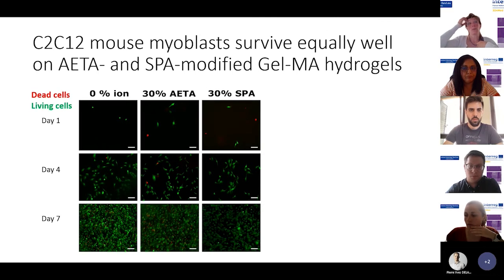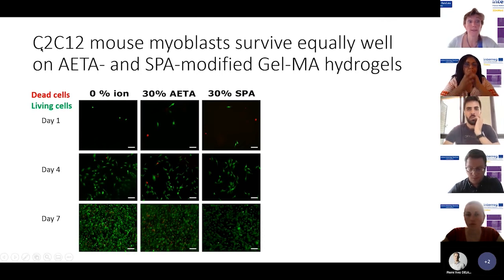And then, of course, the most important part for us was to see whether the myoblasts can survive on the hydrogel. And so we tested C2C12, which are mouse myoblasts, so this we can use to make mouse muscle tissue. And then first of all, we saw that the myoblasts survive equally well on the three types of hydrogels. So this is the standard GelMA hydrogel, and then with the two ions included in the hydrogel. And then there is no difference.